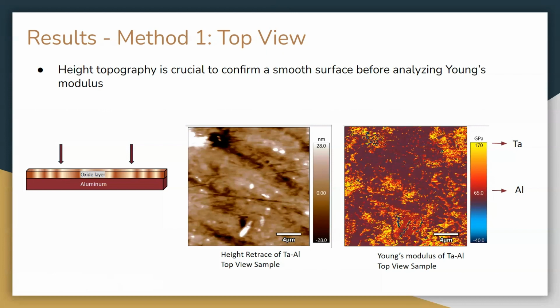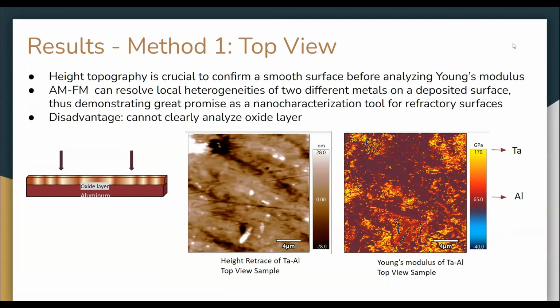And as you can see, it's very clear that this is a top view because you can see that the tantalum is sprayed on around like 170 gigapascals. And then the aluminum is the maroon color, which is around 70 gigapascals, which is the Young's modulus of aluminum. So these results show that the bimodal AM/FM tapping mode for the AFM can resolve local heterogeneities of two different metals on a deposited surface as seen through aluminum and tantalum, but it also demonstrates great promise as a nanocharacterization tool for refractory surfaces. A disadvantage is that because I scanned the results from a top view, this couldn't analyze the oxide layer of what happens underneath the tantalum because AFM is a surface technique.